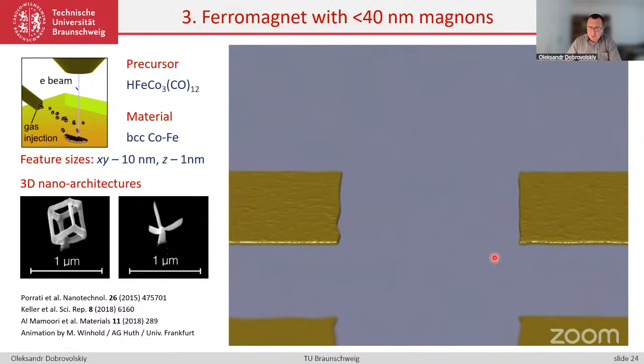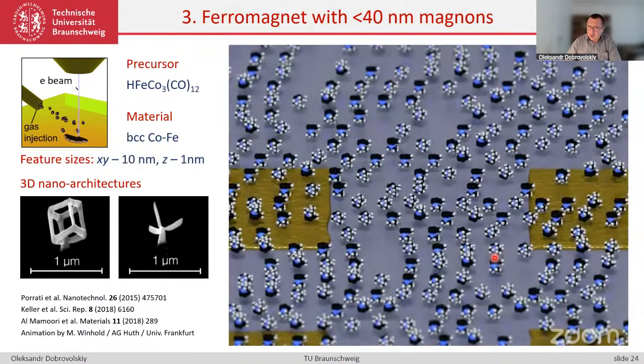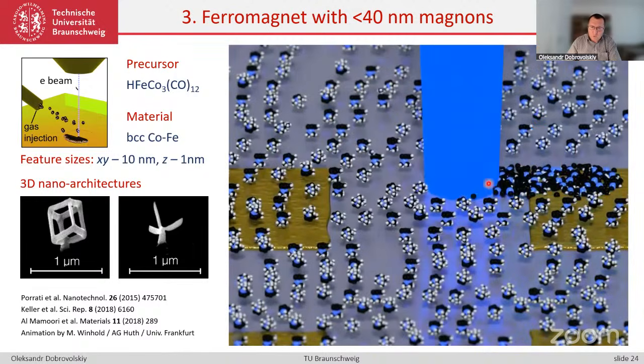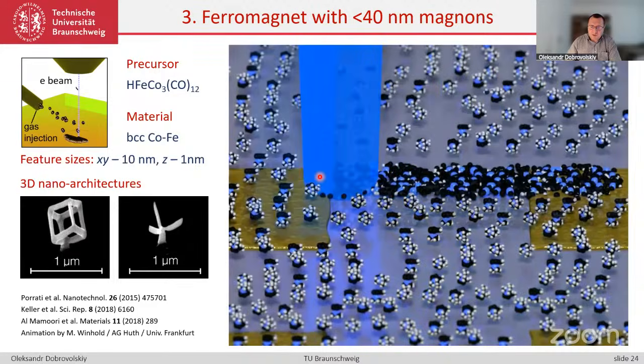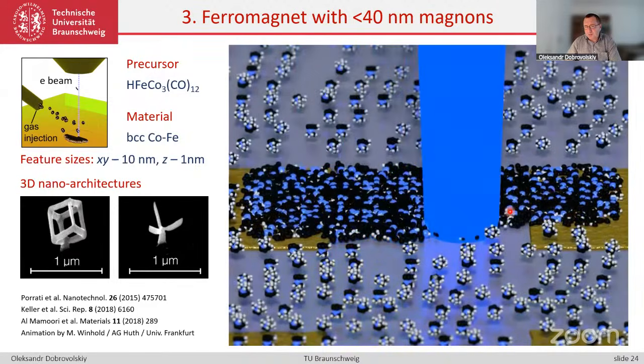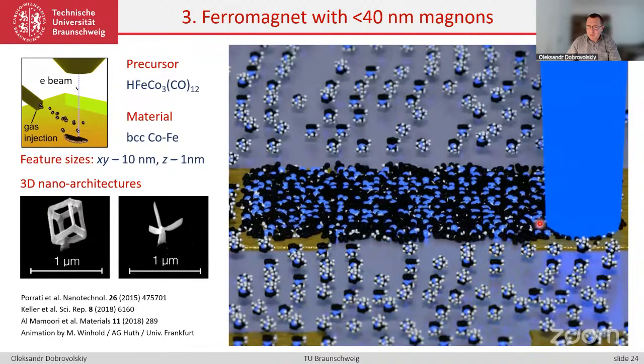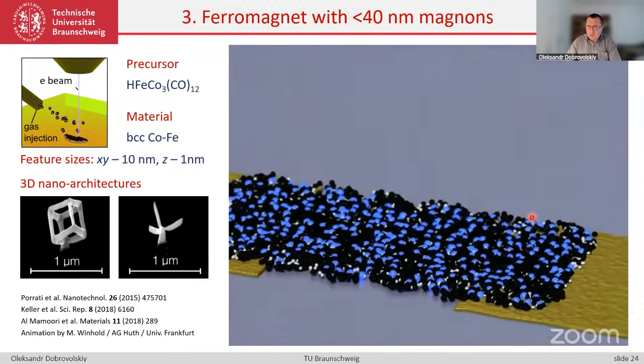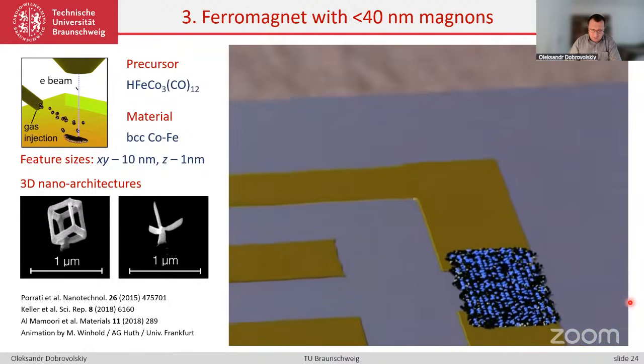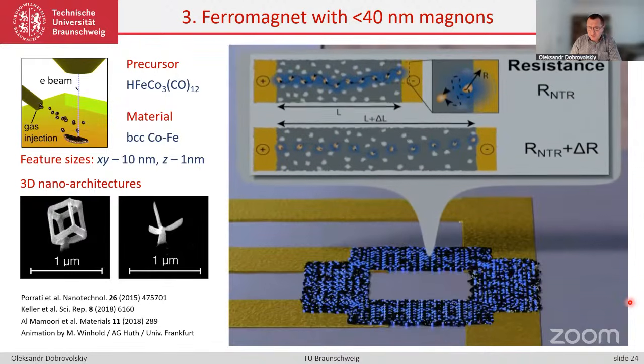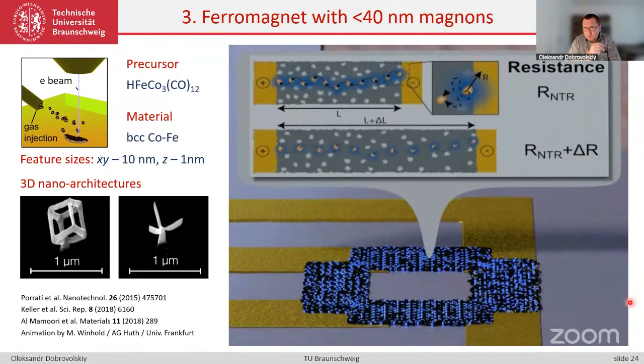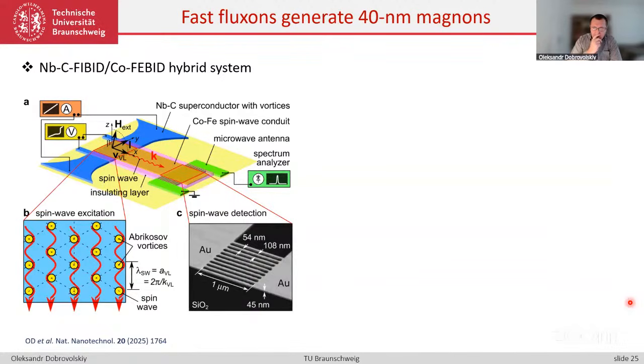The operator defines a pattern file, and then the focused beam is scanned over the surface of the active area in accordance with the predefined landscape. The volatile components are pumped away from the microscope chamber, and the remaining deposit is a sample which then is going to be investigated and used for further studies. In this case, this is exemplified for platinum growth. We use this technique for cobalt iron for the magnetic conduit and niobium carbide for the superconducting counterpart, and combine these materials together. This brings me to the experimental realization of the system.